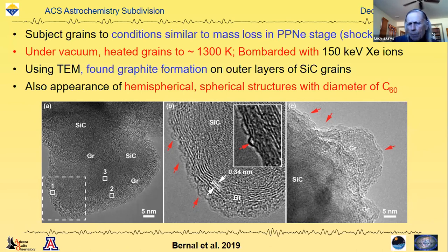It's very difficult to image C60 in a TEM. In fact, one of the few images I could find in the literature was C60 attached to a nanotube. And that's the inset you see in the middle panel. And you can see our little bubbles and hemispheres look exactly like that C60. And they have the exact diameter of C60. And on the right, you see another picture done with the TEM where you see little hemispherical structures, the diameter of C60.